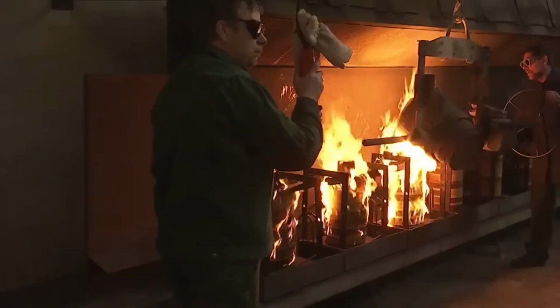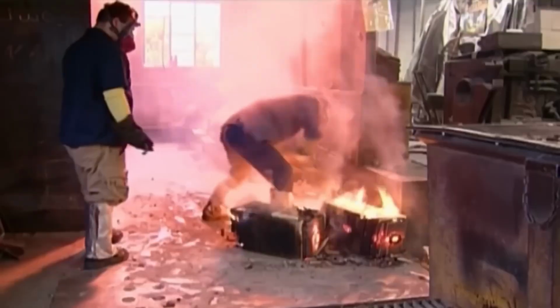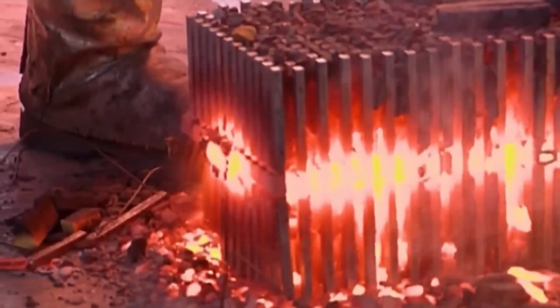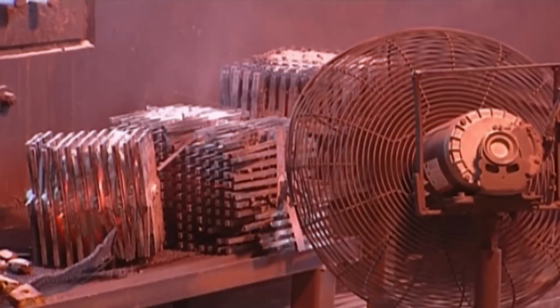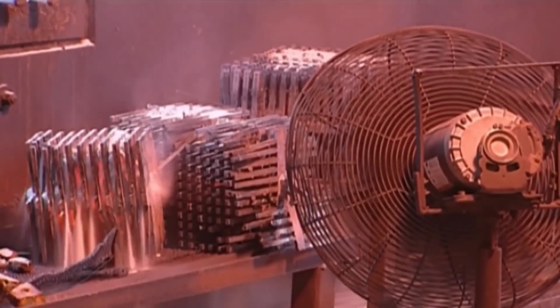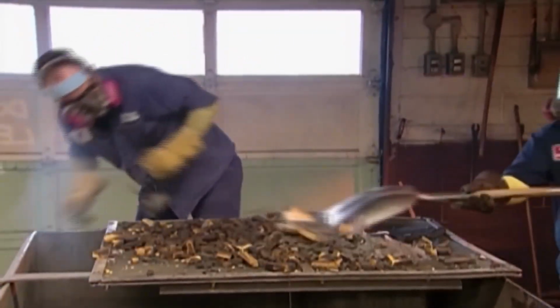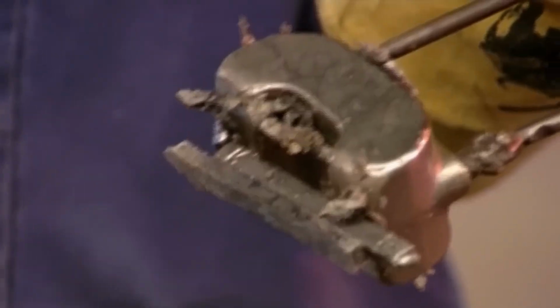After pouring, the molten alloy is left to cool inside the mold. The burning molds are transported to another section of the foundry and dumped onto the floor. During this solidification process, the metal contracts slightly, which is why molds are usually designed with tolerances to compensate for this contraction. Cooling must be controlled to avoid internal stress, cracks, or warping. An external cooling system is used to speed up the process without compromising the metal's structural quality.